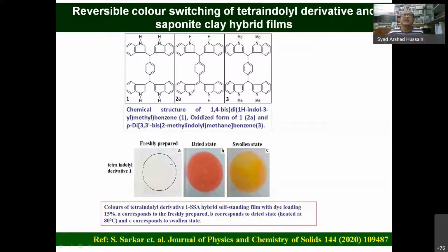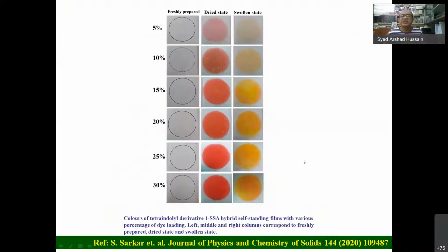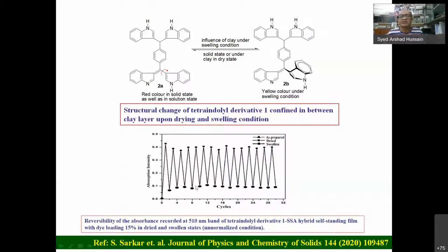Then this is another clay and indolyl system. You see freshly prepared, no color, but when we dried it, due to aerobic oxidation, red color occurred. But in swelling conditions, twisting of the bonding occurs and conjugation is affected, so the color changes. We observed this for different concentrations, and we observed that this is again reversible. You see, so this is very good for optical sensing. And the main point is that with the naked eye one can perceive the change, the sensing.